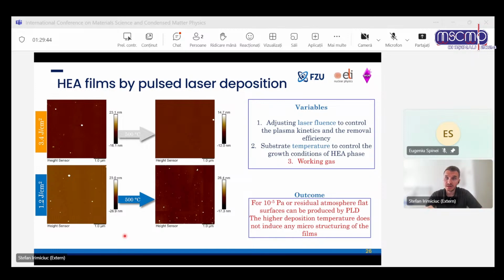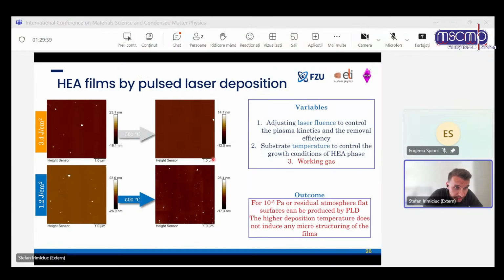For these tests, at least for this particular one, we used vacuum, so 10 to the minus 5. And we didn't see any microstructuring or nanostructuring of the film. The film seemed quite flat. Of course, you can see small clusters, which is specific for pulsed laser deposition, especially for metals, but the films are flat, really flat, and we're really happy.